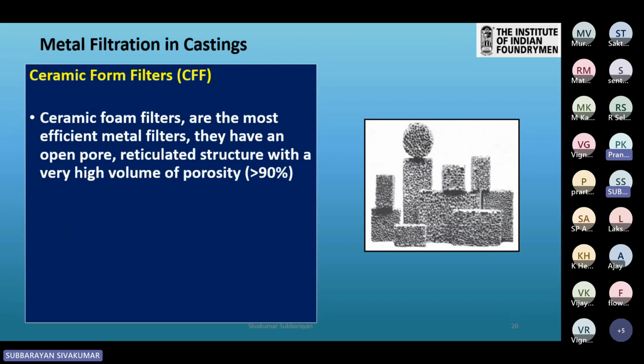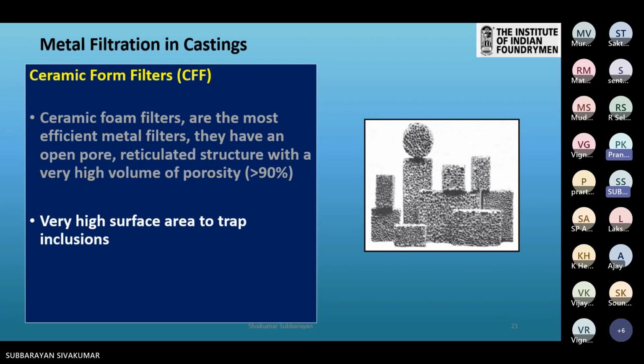Let us move on to the ceramic foam filter. We call it as CFF. This is the filter predominantly used in many foundries with various sizes, various shapes. They are the most effective and efficient metal filters. They have an open pore reticulated structure with a very high volume of porosity over 90%. It has very high surface area to trap the inclusions, and the biggest advantage is that honeycomb structure which is created in the foam filter. It doesn't allow impurities to pass, but in this also any liquid slag is bound to cross.